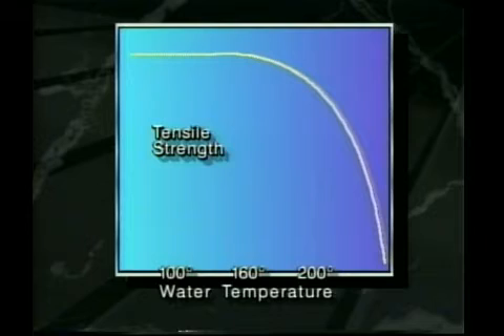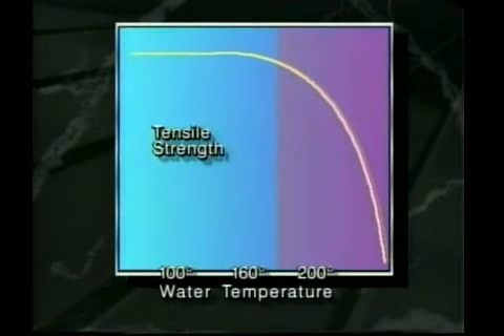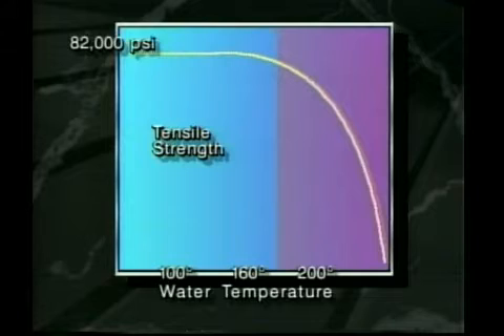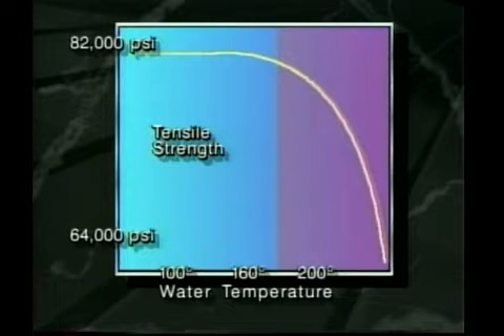It can be seen that as the temperature of the water is increased, the quenching characteristics of the bath are slowed significantly. A significant loss in tensile properties resulted when the water temperature was raised above 160 degrees, as the cooling is not sufficient to freeze in the solute atoms during the quench. An 82,000 pounds per square inch tensile strength was achieved in cold water, while the strength dropped to 64,000 psi when boiling water was used, a loss of 25%. Even high-strength castings can lose properties if the quench water temperature is too high, as shown here.